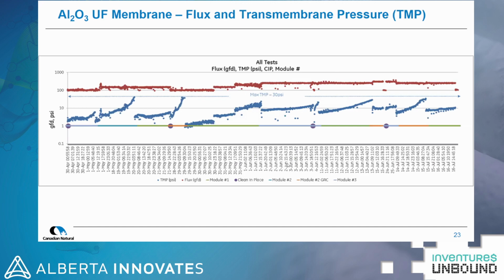So what you'll see here is that as the pressure climbed and hit that upper threshold, either membrane modules were swapped out, we had three modules we were testing, or it was cleaned in place to recover the membrane, and that brought you back to the initial operating pressure. So this work was done to establish the maximum sustainable flux, the optimum backwashing regime, and the cleaning protocol was established before this test was done, and then those operating conditions were maintained as we tried to identify the maximum sustainable flux.